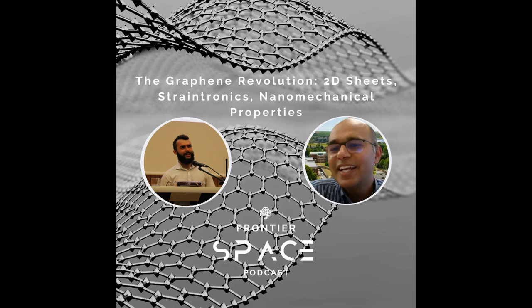So that's a part of the project. These nanorobots could be for civilian application, defense application, anything. It doesn't matter what the application is. The concept is how to protect those nanorobots. So we have done some coating of single layer graphene on this serrated, gear-shaped structure. Then we rub it against another gear structure, through a technique called friction force microscopy, in which you have a coated material and you rub it against another.